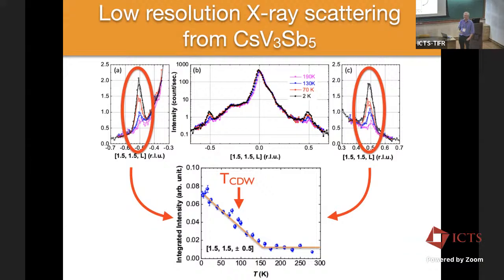It's not what comes naturally to a high resolution measurement. It's not that it can't be done, but it's not what comes naturally. Whereas it is what comes naturally to a low resolution measurement, because if you've got a big integration in reciprocal space and you've got something that doesn't change very much, you're going to integrate a lot of it up.